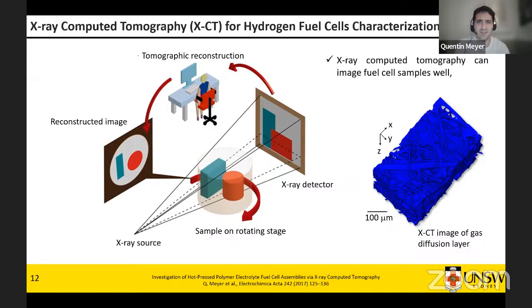And X-ray tomography can image fuel cell samples really well because lab X-ray has a resolution of 1 micron. Fuel cell features we're looking at are in the tens to hundreds of microns. So we get quite a nice image. This over there shows you, if you look at a gas diffusion layer, you get excellent resolution. You can see very well the carbon fibers, how they're bonded together with ionomer, with PTFE, and you can get quite an excellent picture.